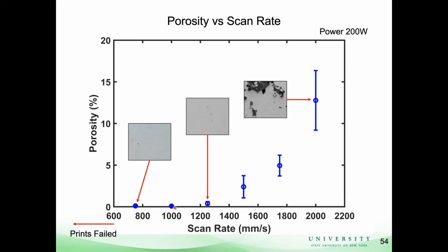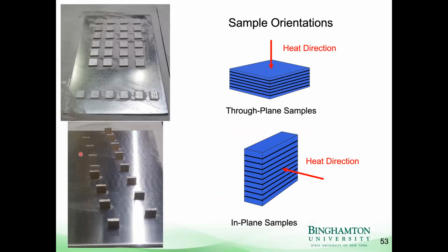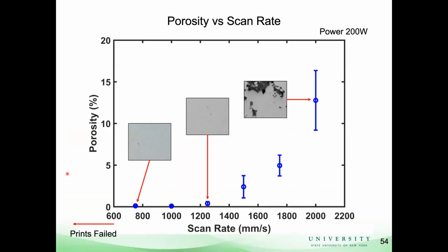So if you print stainless steel with just the EOS default parameters, it'll be around here. If we slow down the laser even further from 750, another step to the left here, the prints will fail. Actually, I'll just go back one slide. You might see that there are some stubs here on this build platform. These are parts that failed because the laser was moving too slowly. If you move the laser too slowly, you're actually boiling a lot of the metal, and that leads to splatter, just like if you're boiling a soup on the stove and you boil it too vigorously, you'll get splatter shooting everywhere. The same thing will happen with metal, and that splatter will create roughness and deformation and lead to print failure. So that's what happened here.